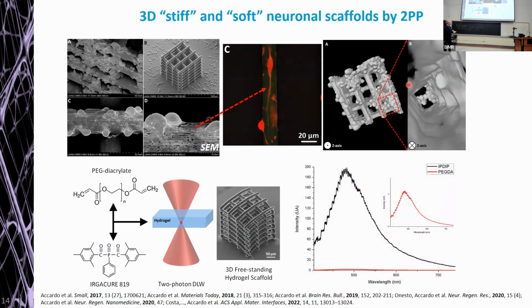Also, the material was very interesting from an optical point of view. You must know indeed that whenever you use 3D cell microenvironments, you will use at some stage 3D immunofluorescence microscopy to track some markers, differentiation markers, proliferation markers, adhesion markers, and so on. If you have a material which is intrinsically fluorescent, then this messes up your work because it will overlap with the fluorescent signal coming from the staining of your cells. In this case, our material, PEGDA, had an intrinsic fluorescence which was more or less 100 times lower than the one of IP-Dip, which is the material that we used in this first publication.